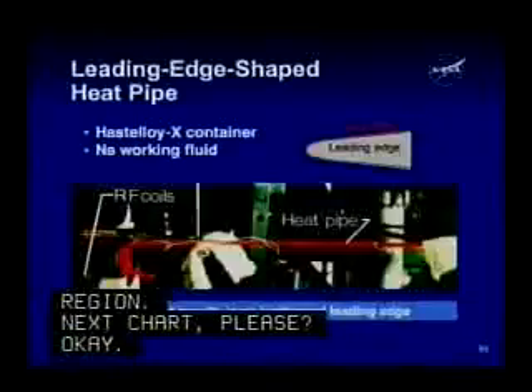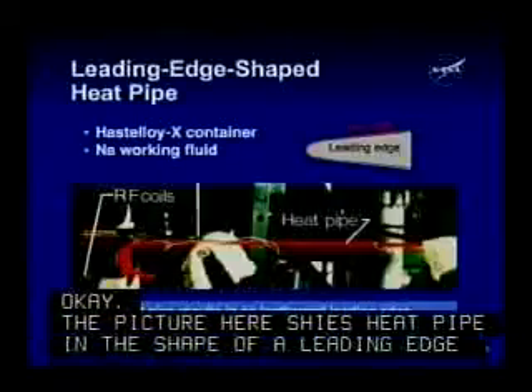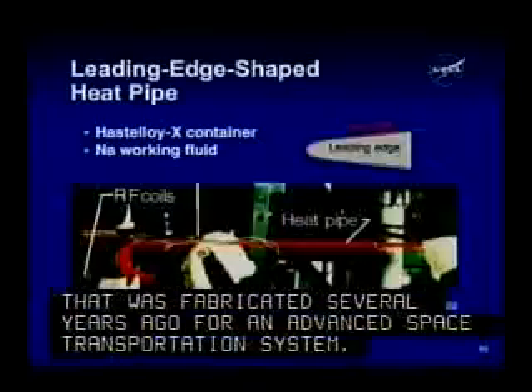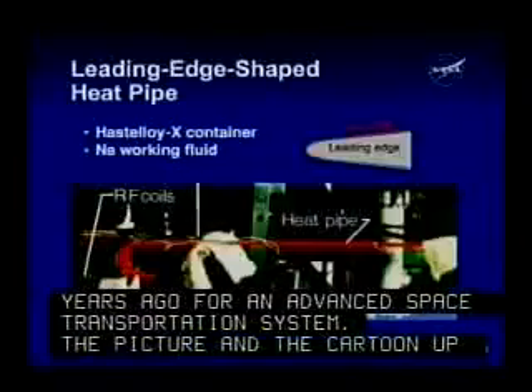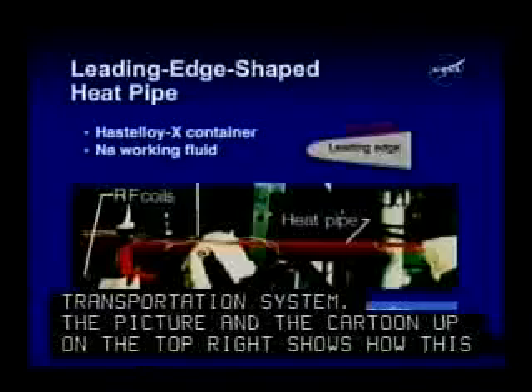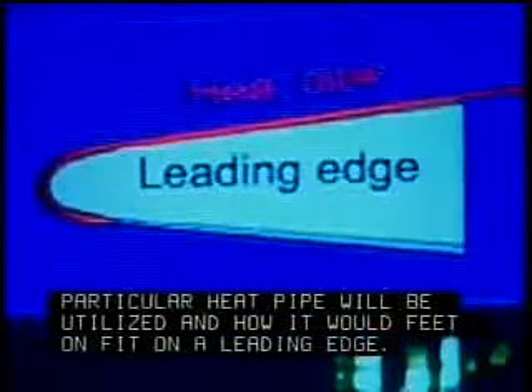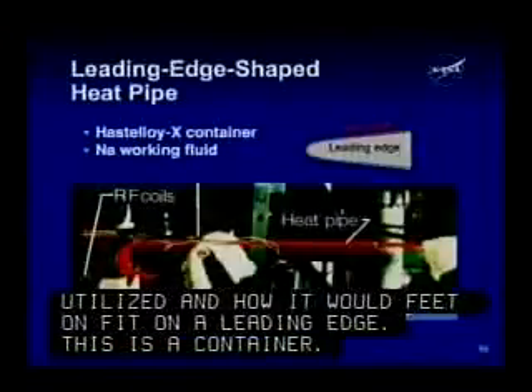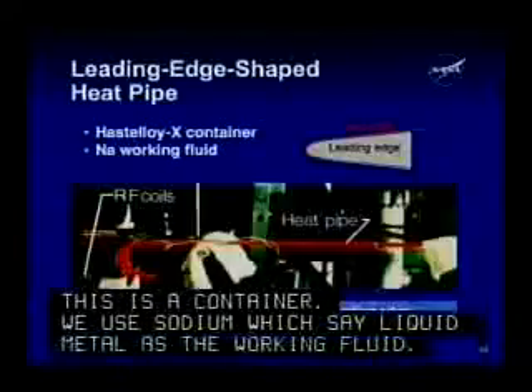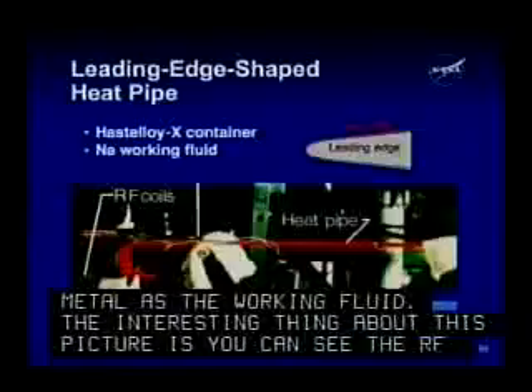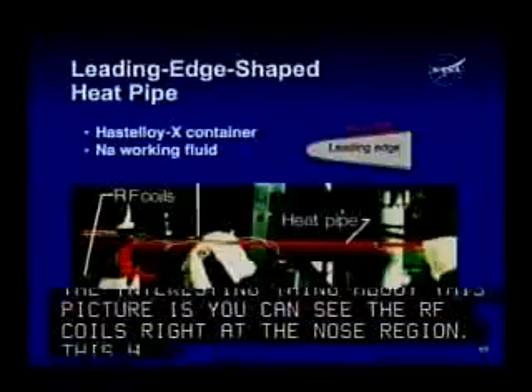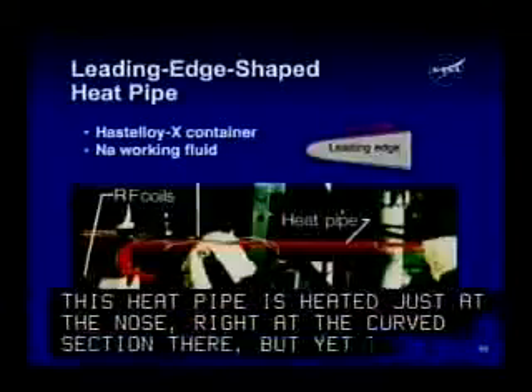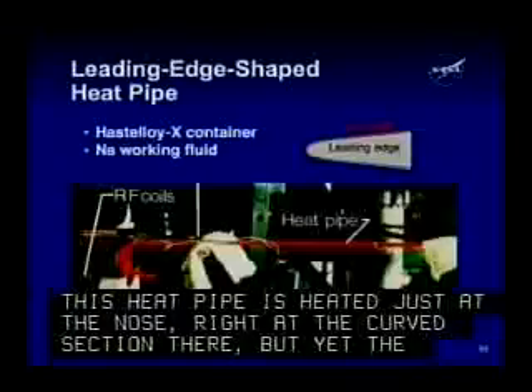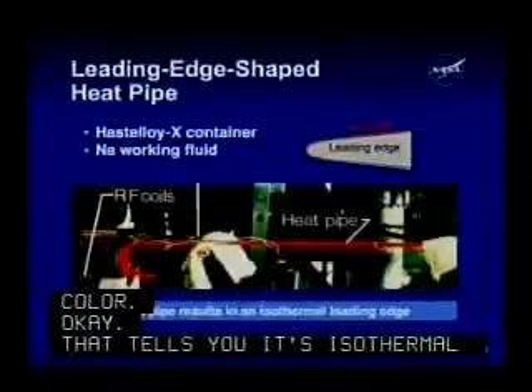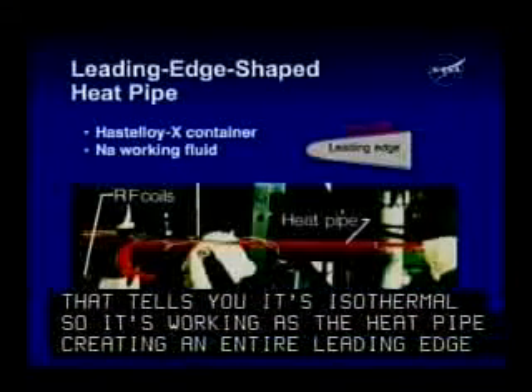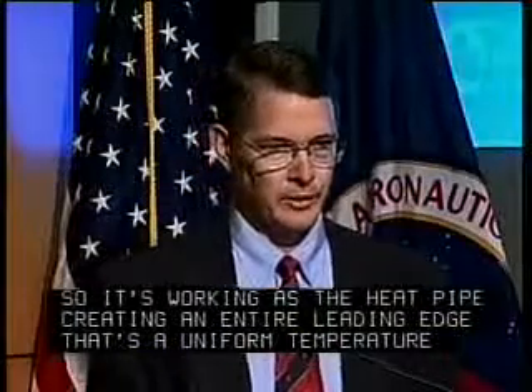Okay, the picture here shows a heat pipe in the shape of a leading edge that was fabricated several years ago for an advanced space transportation system. The little cartoon up on the top right shows how this particular heat pipe would be utilized and how it would fit on a leading edge. This was a Hastelloy-X superalloy container. We used sodium, which is a liquid metal, as the working fluid. The interesting thing about this picture is that you can see the RF coils right at the nose region. This heat pipe is heated just at the nose, right at the curved section there, but yet the entire heat pipe is the same color. That tells you that it's isothermal. So it's working as a heat pipe, creating an entire leading edge that's at a uniform temperature when it's only heated just at the nose region. Next chart, please.